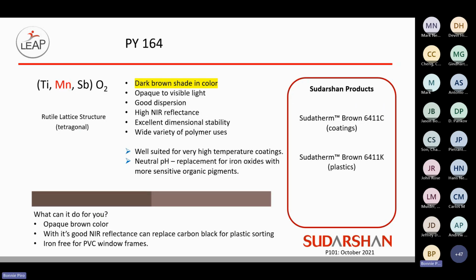And continuing even redder, if you will, is Pigment Yellow 164, although it's a misnomer because the color of it is so brown. It's a very interesting dark brown color. There's a wide variety of polymer usage for this particular one. It has a very interesting property where it has a very neutral pH, so it's a potential replacement for iron oxides where the organic pigments in the formulation might be sensitive to pH. And the other property that is kind of interesting is that it is iron free. So for PVC window frames, it doesn't have that attribute that you can find with iron containing pigments.